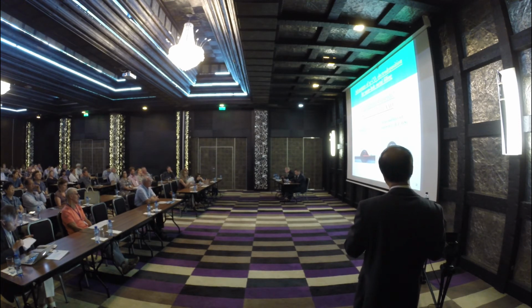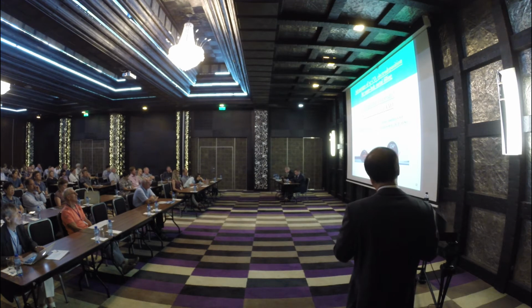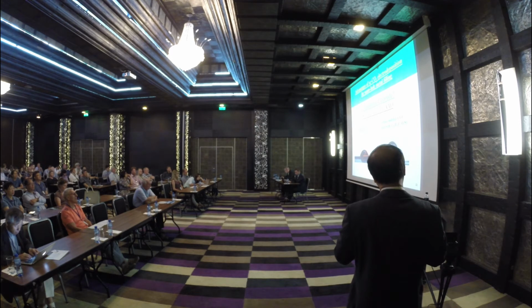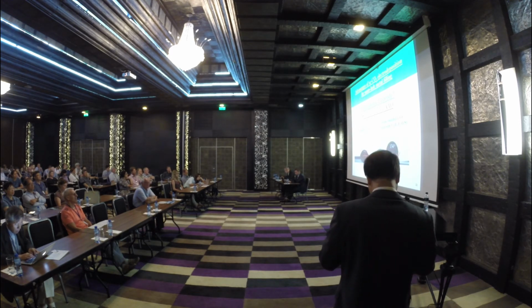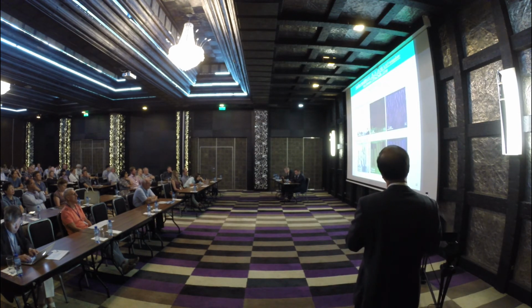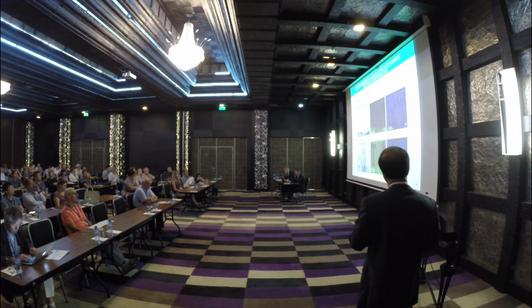So for as-anodized AO, we modify the wall surface by immersing in this electrolyte, to try to change the surface tension. And this is the as-anodized, with low surface tension for aqueous electrolyte. But when we modified AO with these chemicals, we can see a significant change in the hydrophobicity. And with this, we then apply the deposition process again to compare the difference between the conventional processes and the supercritical carbon dioxide electrodeposition process.